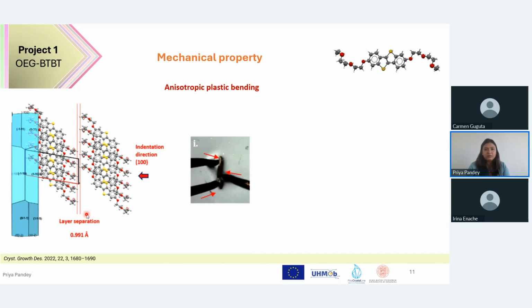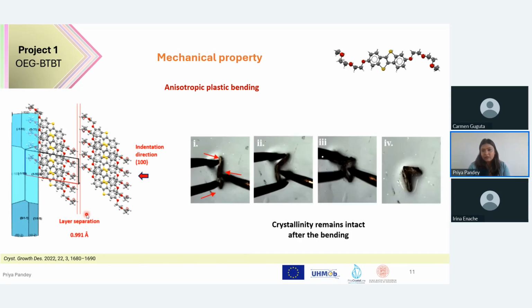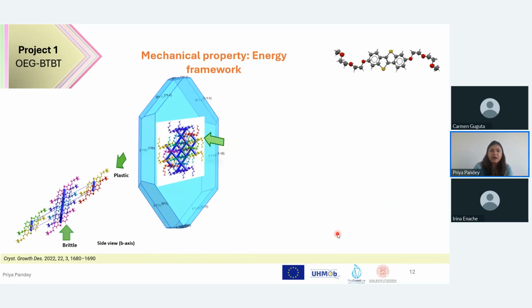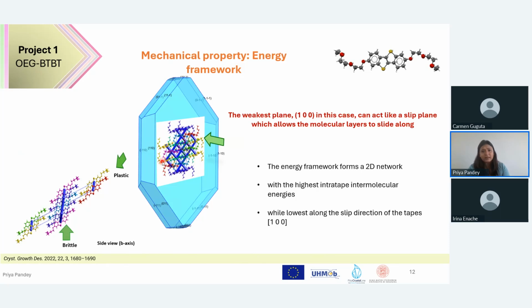I tested it experimentally, and the crystal remains intact, and it was bending instead of breaking. To get to know the reason for this kind of bending behavior, I also carried out some energy framework analysis. So basically, the tubes you can see illustrate the extent of energy that is there. You can see that it forms a 2D network, intraplanar, intralayer, and very less thick tubes are present interlayer, which means that the weakest plane in this case can act like a slip plane, which allows the molecular layers to slide along.